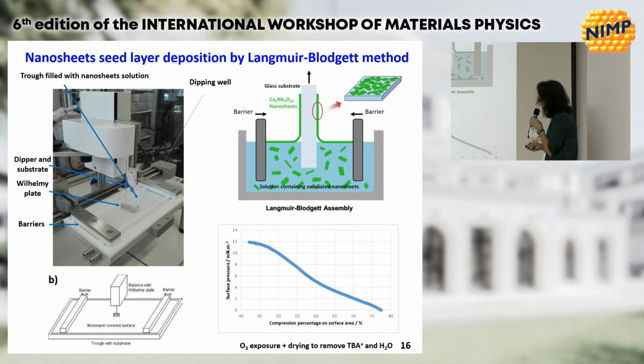So next, to transfer the nanosheets to a substrate, we can use two methods. The first one is the so-called Langmuir-Blodgett method. This is a very old method to deposit organic particles. Yet it is used for the deposition of nanosheets. So the principle is, we put in this container the liquid, the colloidal solution. Here we have a hole, which is a dipping well for the substrate, which is here. So we can dip the substrate in here.